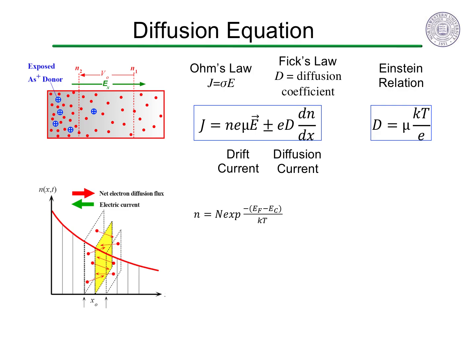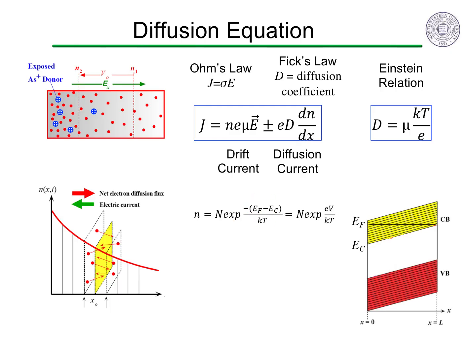For a semiconductor where Boltzmann statistics is a good approximation, N is related to the exponential of the energy difference between the Fermi level and the band edge divided by kT. In equilibrium, we saw this energy difference is related to the electric potential energy EV. Equilibrium also requires the drift current to exactly cancel the diffusion current. This requires the mobility to be related to the diffusion coefficient times the relative change in N per change in V, which becomes d log n dV. This is simply E over kT, giving the Einstein relation.